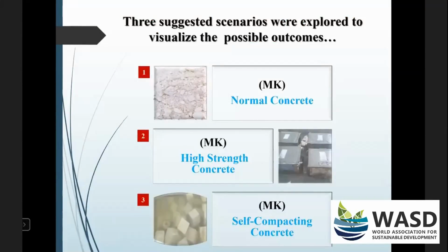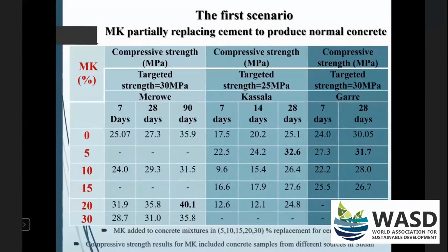So after checking the suitability of the calcined kaolinite clay in comparison to ordinary Portland cement, we wanted to use it in our concrete mixtures. So 3 scenarios were explored to visualize the possible outcomes. We used the metakaolin to produce normal concrete, high strength concrete, and self-compacting concrete. With the first scenario, the metakaolin was added in concrete mixtures in different percentages. We started with 5, and then went up to 10, 15, 20, and 30% as a replacement for cement.